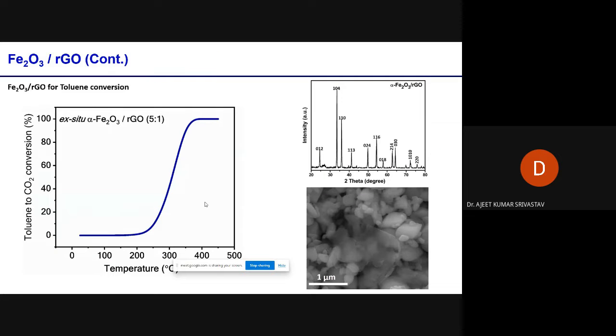And another application I can show you is where iron oxide and graphene are used for volatile organic compounds, which are hazardous to the environment, to change them into a non-hazardous kind of product. Here we use toluene to CO2 conversion. We showed that if we use this hematite and graphene, we can change toluene completely to CO2 at almost 350 degrees centigrade. On the right side, this is the X-ray diffraction of the hematite and graphene nanocomposite, which shows the intact hematite phase structure, and the morphology where you can see the particles along with graphene in the SEM micrograph.